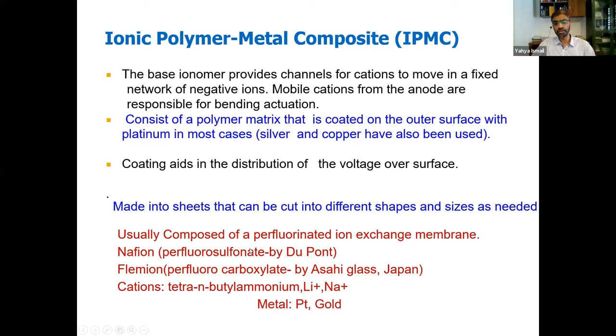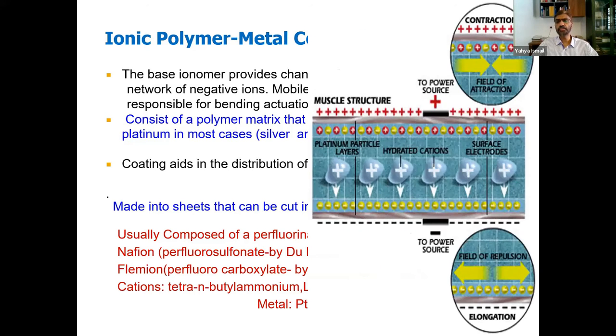Usually Nafion, because the DuPont product Nafion was first used for producing the IPMC based actuator, usually composed of a perfluorinated ion exchange membrane. Then Flemion from Asahi Glass, their brand name is Flemion. Nafion is the brand name from DuPont. Bigger cations and smaller cations are used, and the metal coating is from platinum or gold. And this is a schematic representation of the mechanism in which the ionic polymer showed movement.